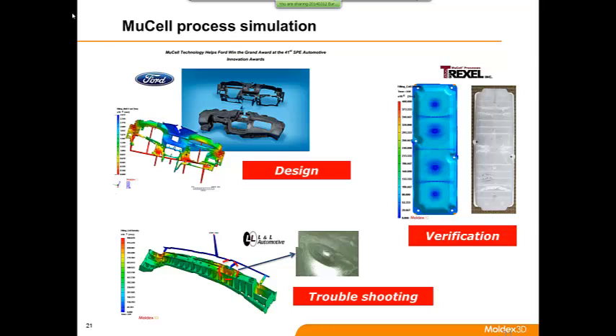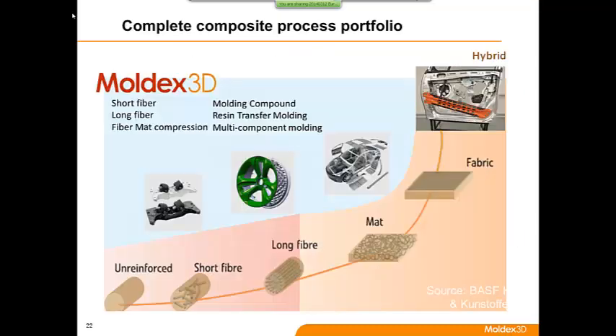So this is one of the examples of the mu cell. Right now, the technique is still very new. You have to use the specialized equipment to finalize in making the supercritical fluid and to inject it in your resin. But we already see a lot of applications, and Moldex3D can help you during the design stage, verification stage, and also even on the troubleshooting stage. For example, here you see the bubble is too big, so it's like a burp on the surface. This is from the simulation. We find out that this is due to a really high temperature causing the cells to grow too fast and causing these kind of problems. So all these things can all be simulated and validated through the software.